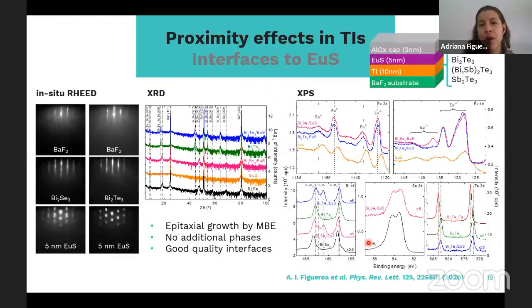And then for that, we grew our layers. So as I showed you on the MBE chambers that we have, we grew our topological insulator layers, which are of this bismuth, antimony, tellurium, selenium family. So we grew a series of these samples, and then we transferred them in vacuum to the second chamber to evaporate europium sulfide on top. We had no additional phases. We have good quality of interfaces as demonstrated by XPS analysis as well. And then we took these samples to the synchrotron, and then we did our study.